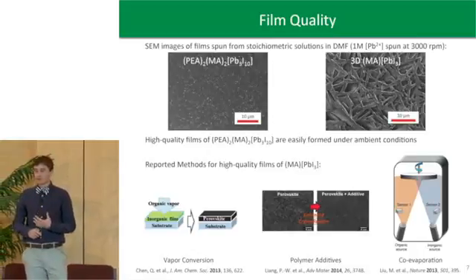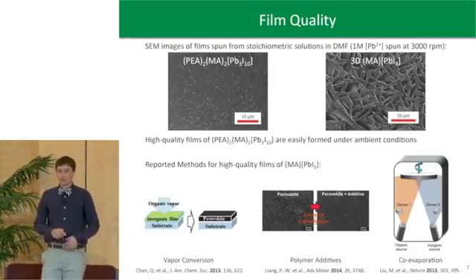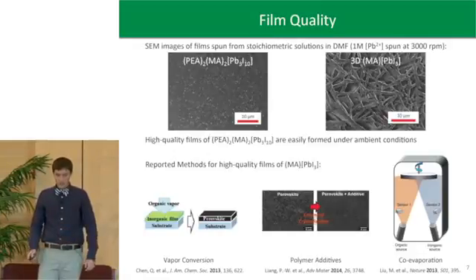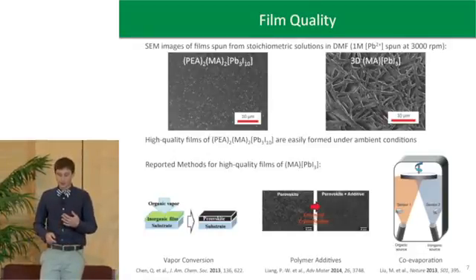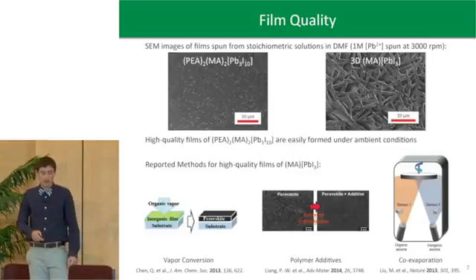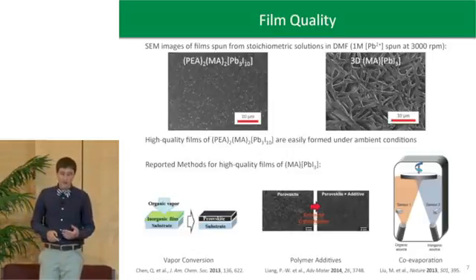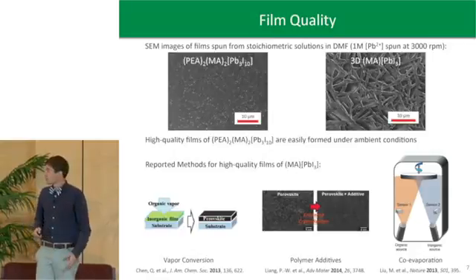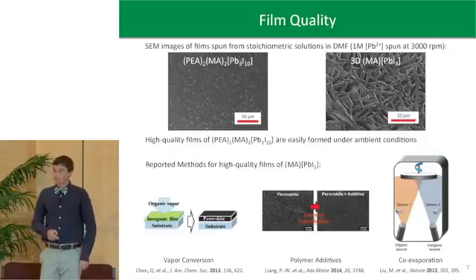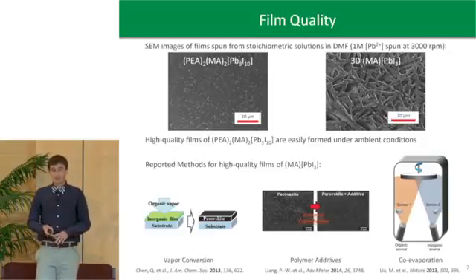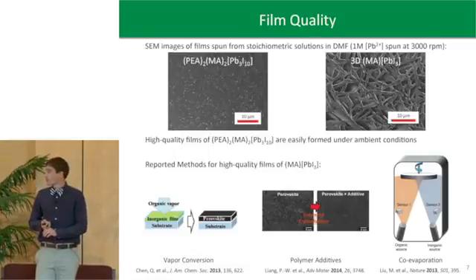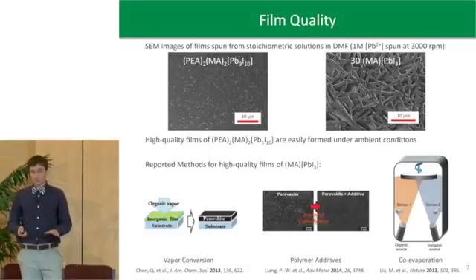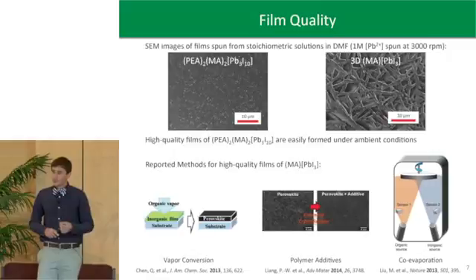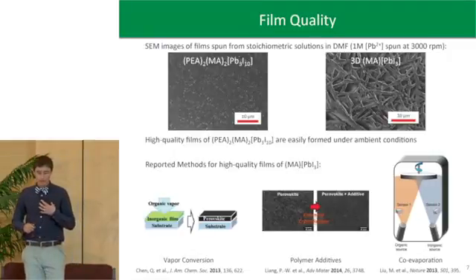So making films of this material is very easy. We use a single-step solution spinning step from a 1 molar lead concentration in DMF. Shown here on the left is an SEM of the N=3 material, and it's really hard to see much because it's really flat. But if you try and do the same technique with the 3D perovskite shown there on the right, first of all, you need to anneal it to actually form the material. So that's one step that's extra. But also, even when you do that, there are holes all over the film, which is not good for a thin film device. You can make nice films with a three-dimensional material. However, they are much more difficult.